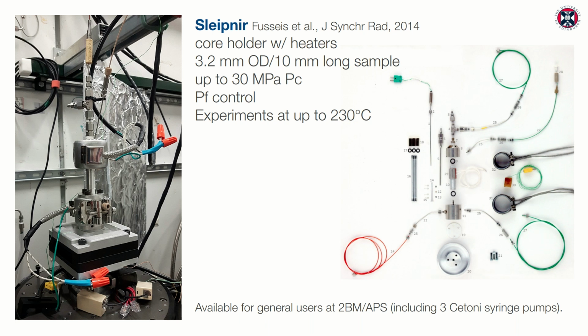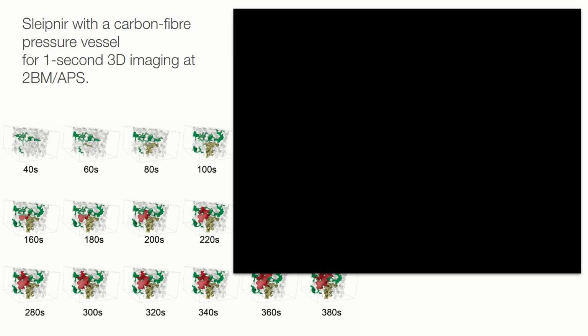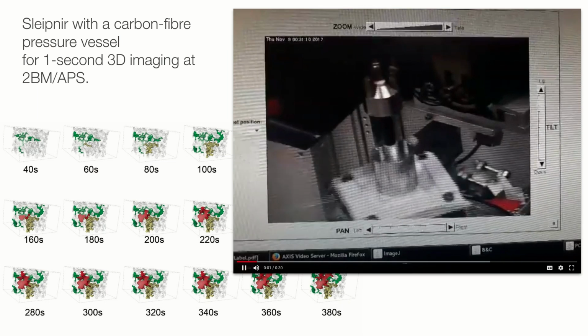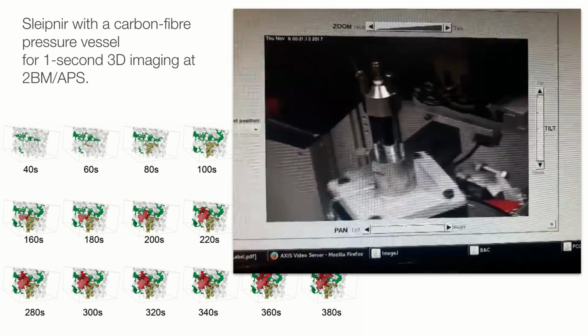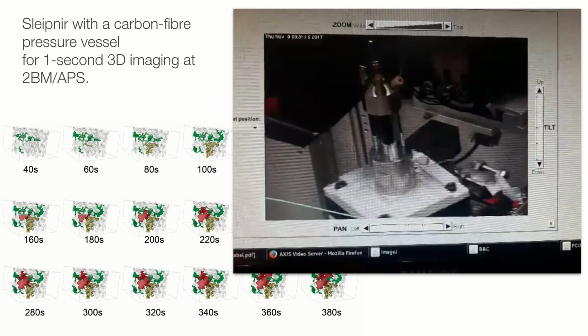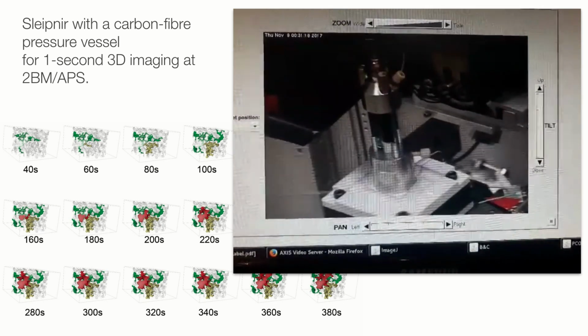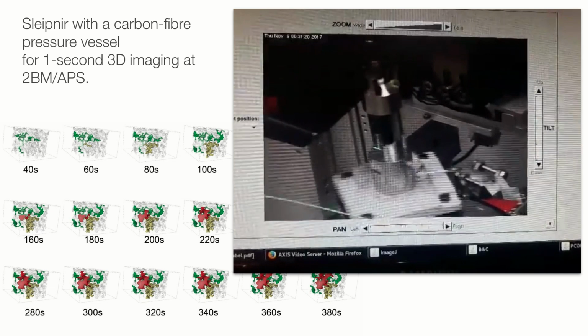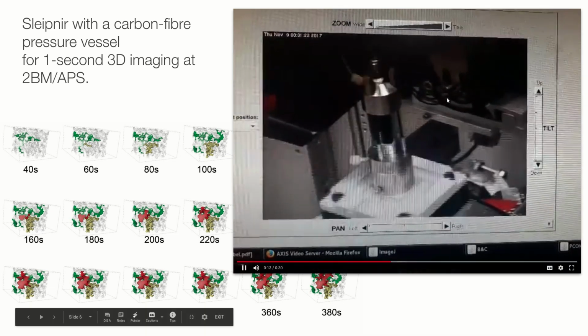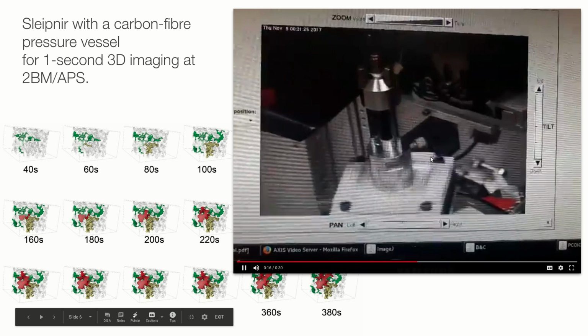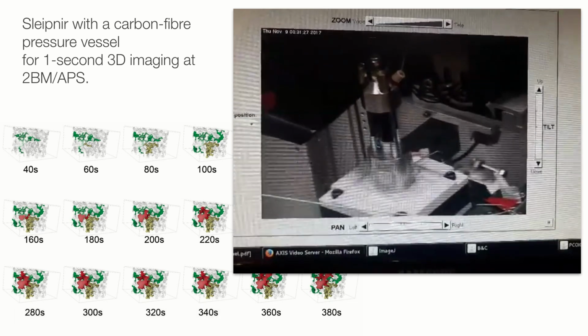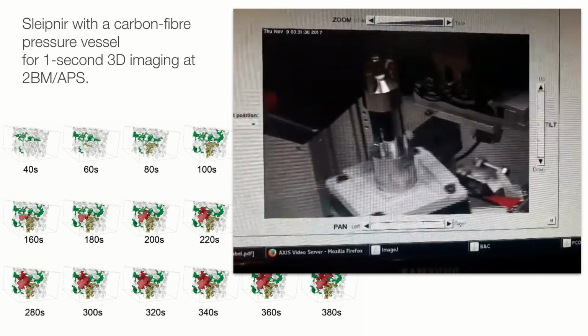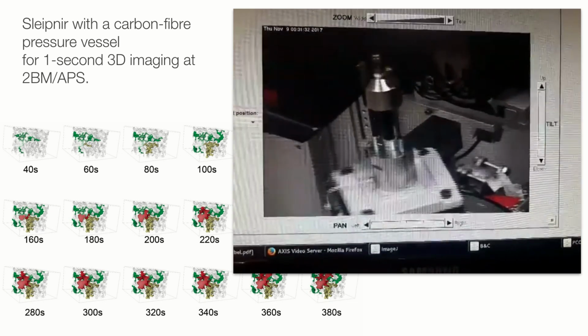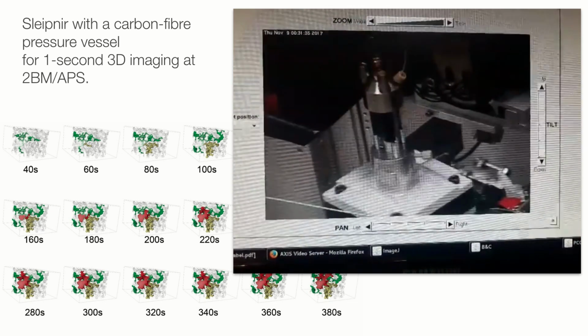As I said earlier, the modularity of our cells allows us to adapt them to specific experiments, and this here is a movie from a very fast 1-second tomography experiment where we injected fluids into a limestone, and we wanted to monitor a displacement front in the sample, where we have replaced the aluminium pressure vessel with a carbon fiber pressure vessel to make this cell really ultra transparent. In fact, in this setup it could also be used in a conventional lab CT scanner. You don't need a synchrotron for that, right?